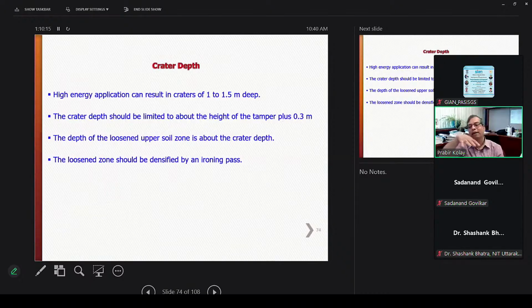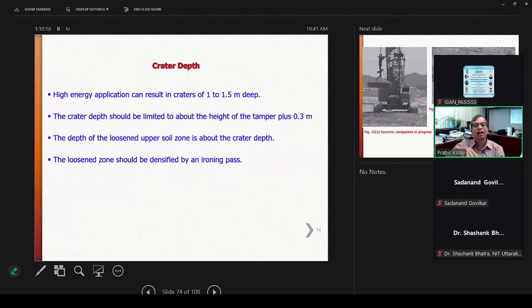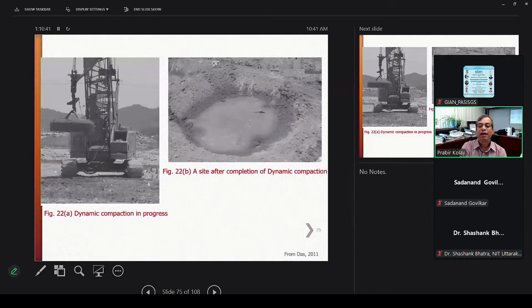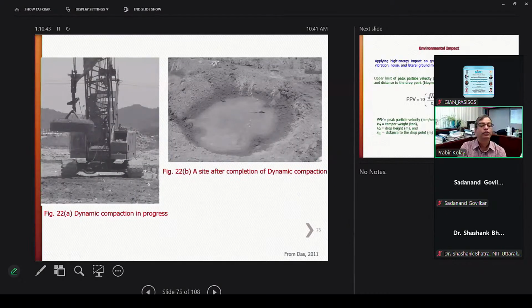All right. The crater depth. So when you impact it, causing a crater, high energy applied can result in a crater of 1.2 to 1.5 meter deep. Crater depth should be limited to height of tamper plus 0.3 meter. The depth of loosened upper zone is about the crater depth again, and then the loosened soil zone should be densified by ironing pass. Okay, so a few things you need to check, and this is how it looks like after dynamic compaction. As I mentioned, it should be filled with sand later on, and then place your actual structures. This is the hammer.